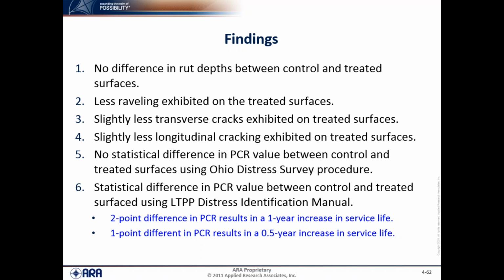There was less raveling exhibited on the treated sections in general. But again, remember I said that there wasn't a lot of raveling, and that raveling was very localized to specific project 3. There was slightly less, and I emphasize the word slightly less, transverse cracking exhibited on the treated sections for all the projects. There was also slightly less longitudinal cracking exhibited on all the treated surfaces.